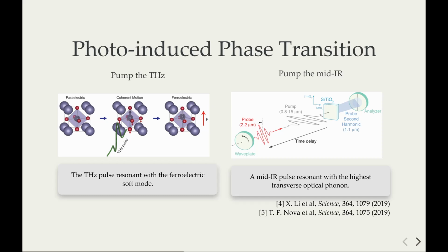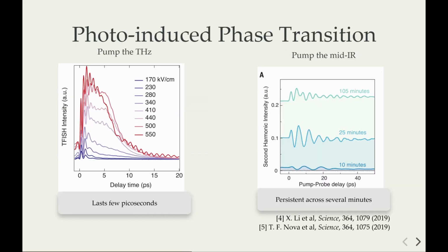This is an indication that the system underwent a ferroelectric transition, which is very strange if you think about it, because usually if you give energy to a system, you expect it to heat up and disorder. In this case, we're giving energy to the system and it's ordering instead, transitioning from a paraelectric to a ferroelectric state. This is very interesting because it's clearly a non-thermal effect.